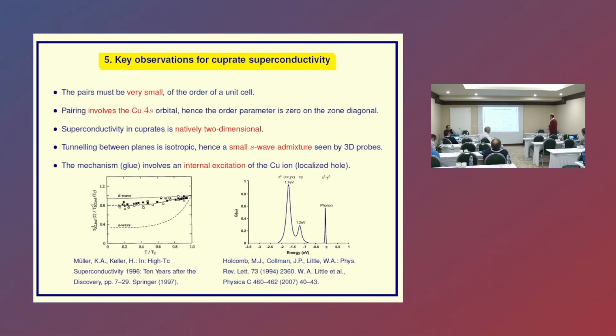Okay? And finally, the mechanism then involves this local hole, but we do not know yet what internal excitation of the Cu ion is involved. And again, there is a 94 paper by Little and his group, and they repeated this in this conference in 2007, where they identified two excitons which are good candidates for the localized glue. And interestingly enough, this experiment was also noticed by Müller, who said that could probably be the glue. Okay, so there is a picture of a localized glue for these holes which propagate via the 4s orbital.